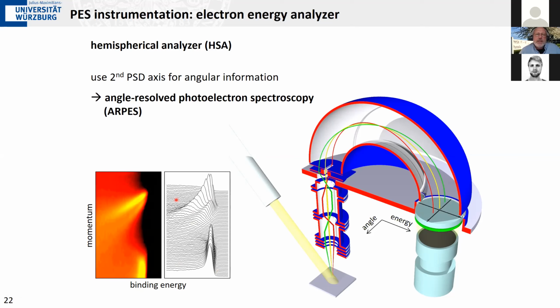This is the same set of data now shown as actual spectra measured at different momenta. Again, the horizontal line is the binding energy axis, and the vertical now is the intensity. But here I stack spectra taken at different momenta. This is how we can map out a band structure.